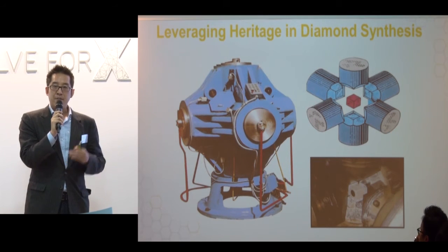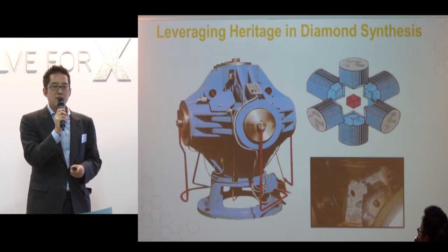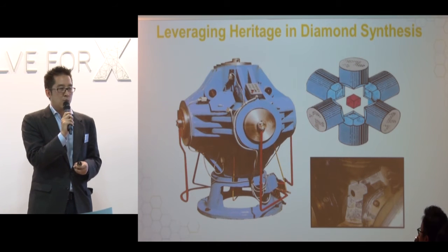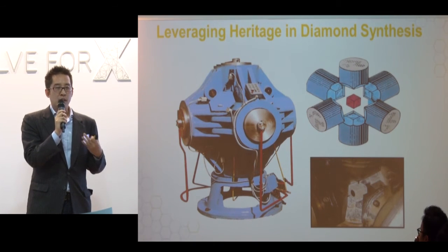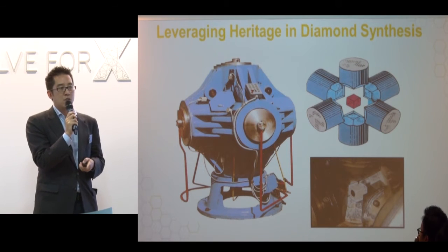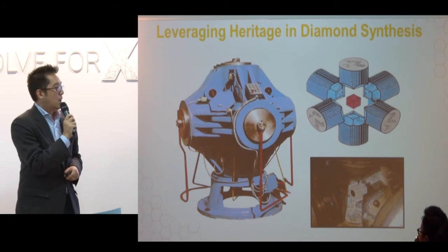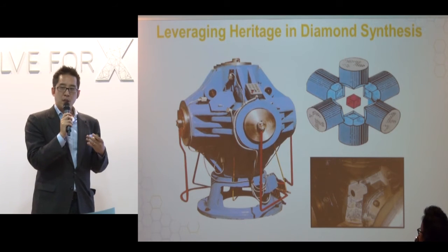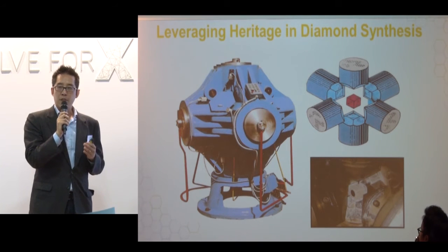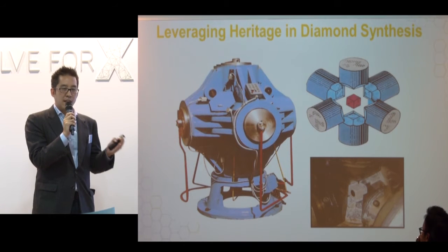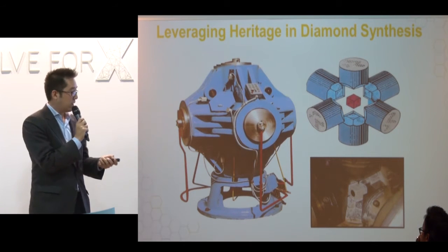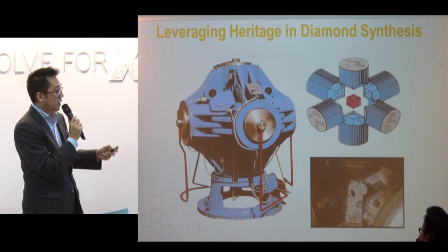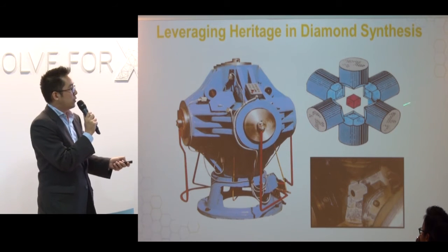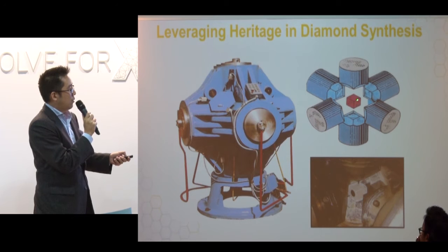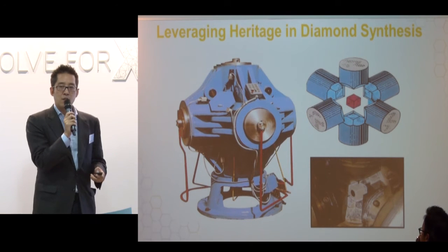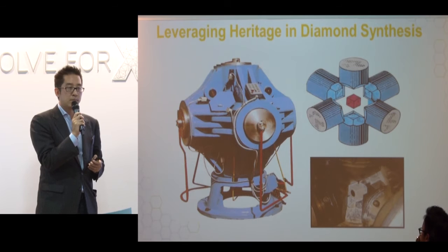My father actually is a very famous diamond synthesis expert, and we have worked on diamond-related technologies, carbon-related technologies for the last 3 decades or so. We are basically appropriating a completely new method for producing graphene, taking tricks of the trade from the diamond industry. So this right here is a diamond press. It's called a cubic press. And what we do is in the middle of this, we mix a little bit of what we call Invar powder. It's a little bit of iron and nickel alloy as a catalyst.